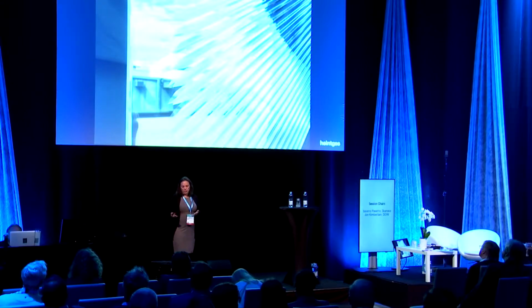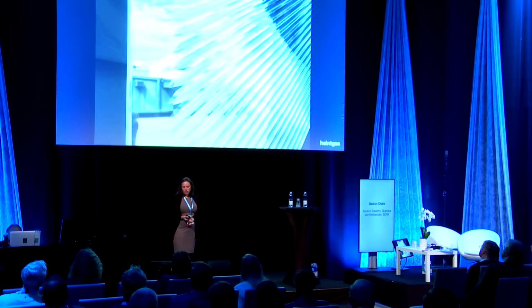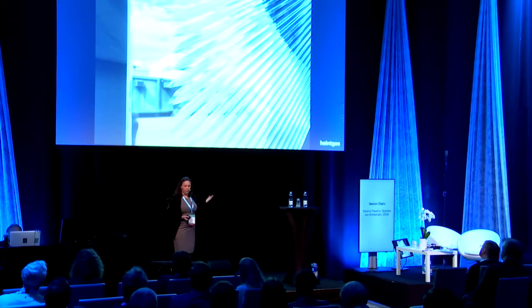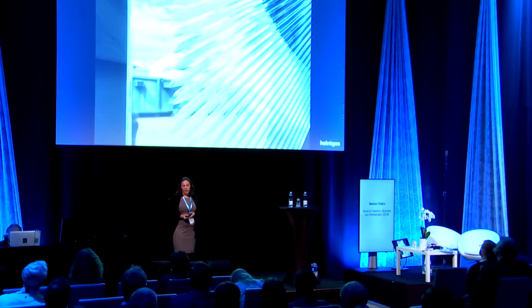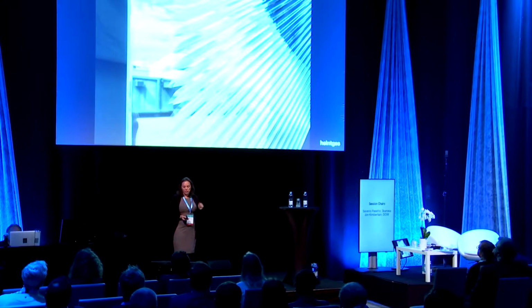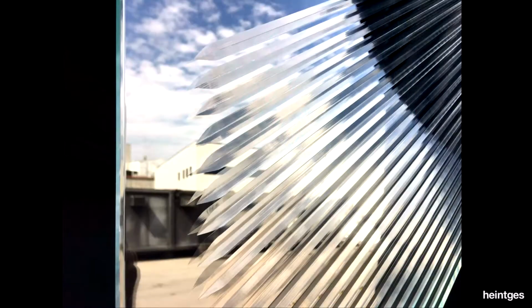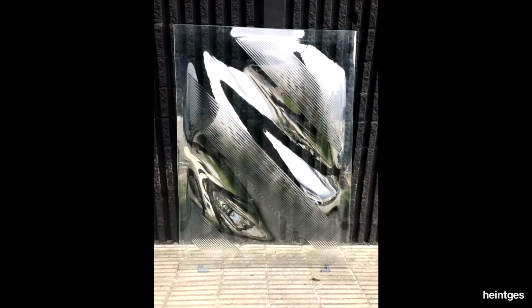So Precursor, in their factory in Barcelona, began working on a number of trials. This is a view of the micro pattern, which was created by carving shallow grooves on the #1 surface of the glass, carving and polishing with a CNC machine. And then this is one of the first photographs we saw of a small size sample of this first prototype, where that carved glass was then gravity slumped on a mold to create the waves and come down to the flat border at the perimeter.